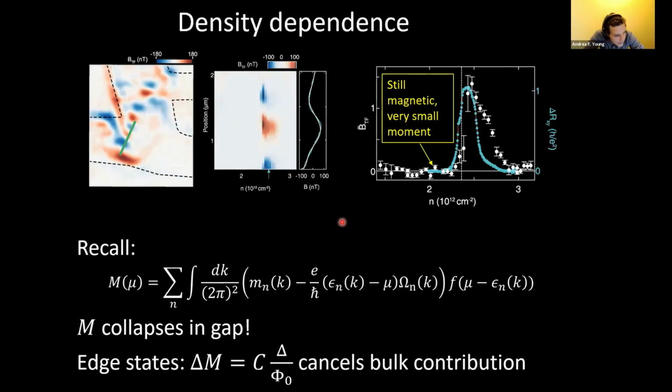We don't think the interplay with elastic degrees of freedom is very likely because the strength of the structural pinning is very big and the energy differences between these interacting states are extremely small. So I actually think that magnetostriction or things like that seems to me kind of unlikely, just because the energy scales are so far off. But the electron system certainly can break lattice symmetries.